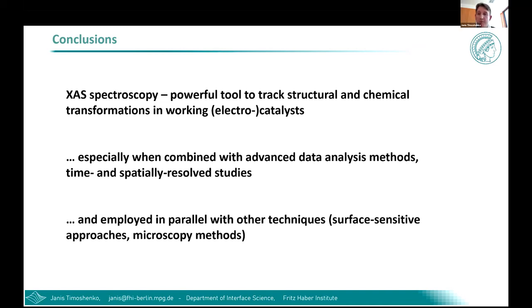Yes, sure. Another great benefit of X-ray absorption spectroscopy is that spectra can be modeled quite well. Especially for the EXAFS region, the mathematics underlying the oscillations is understood quite well, so we can model them very accurately. For the near-edge structure, for XANES, it's a bit more complicated, but it's still possible to model them and use it to establish the relationship between spectral features and structure. As a result of such modeling, the accuracy typically is a bit lower and the calculations or simulations are a bit more sophisticated. But yes, that's an important advantage of this method in its application for quantitative studies.